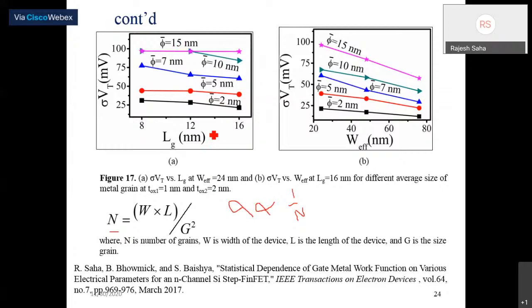Because in that case, the number of grains within the gate area is very small. It may happen to be only 1 or 2. Because the gate length, suppose 16 or 12 nanometer, is almost equal to the grain size. That's why the threshold voltage got saturated irrespective of the gate length for a grain size of 15 nanometer.